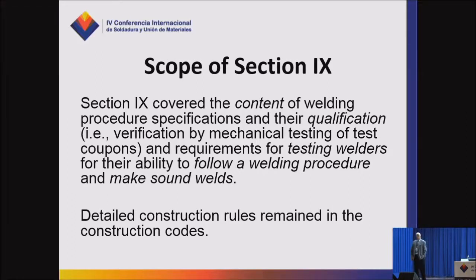how to write a welding procedure, that is the technical content of the welding procedure specification, the welding procedure being direction that the welding engineer provides to the welder, and the qualification of that procedure, which is basically a test that demonstrates by mechanically testing a test piece that the joint will develop a strength level that is comparable to the base materials being used for the test piece. It also contained requirements for testing welders, for testing welding operators at that time. We'll talk more about that later, for their ability to follow the welding procedure and to make a sound weld.